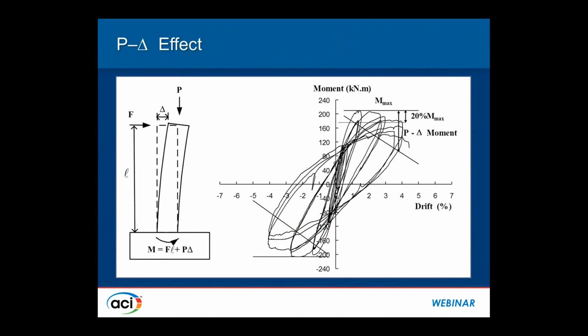When we look at a typical force deformation hysteretic relationship, the effect of axial load has to be clearly identified. In a real building, axial load is vertical in nature, but in testing, often we connect the lower end of the actuator to a strong floor and pull the specimen down, which means the axial load direction will change during testing. This is also true if we use vertical pre-stressing to apply axial load. One has to be conscious of the fact that the axial load inclination will always change, and make sure that when we report the vertical component of axial load, we perhaps subtract the horizontal component of axial load from the force recorded by the horizontal actuator, because the difference is what the specimen is seeing.